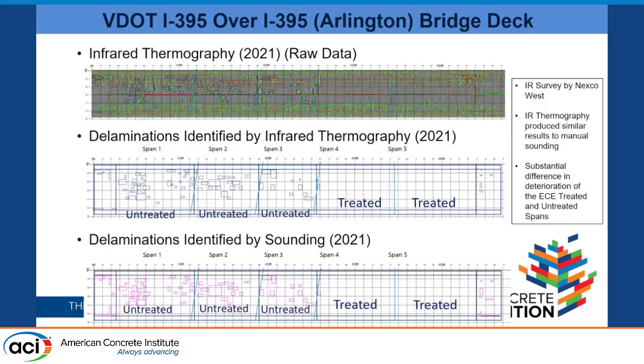This is the delaminations that were identified by the infrared thermography on the 5 different spans of the deck of the bridge. And then VDOT did a hammer sounding survey to verify the infrared results, and they're basically the same. And the 2 spans that were treated as part of that project back then are the 2 on the right, spans 4 and 5. And so you can see, in terms of actual concrete damage, the difference between the treated and untreated ones.